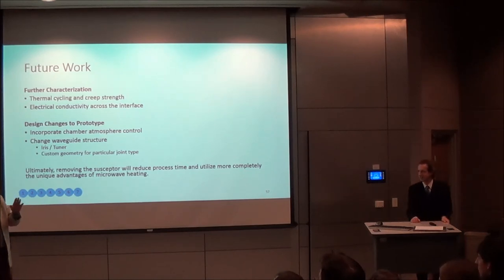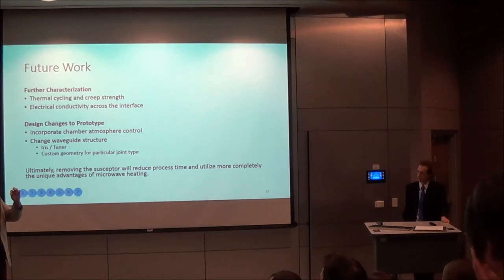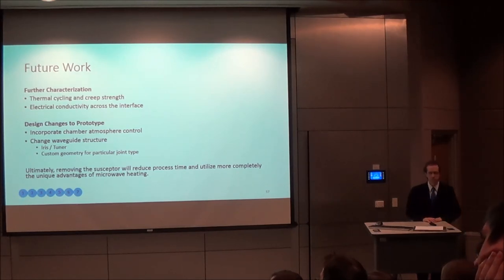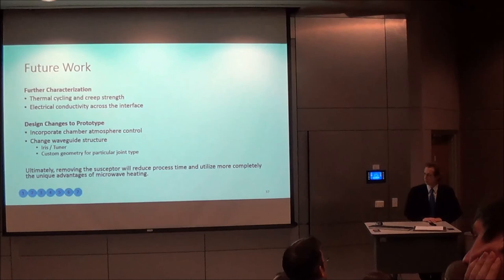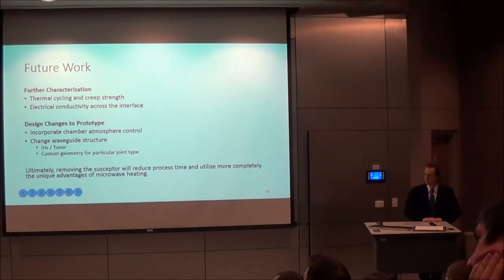Judah, you might remember, I don't know if you were there with Alan, he started with particle size and distribution, magnetic versus paramagnetic powders at the interface. And when they discovered that practically, right now, this composite, this particular dielectric for the powder is almost invisible. It basically reflects everything. We need to find a way to penetrate within that boundary, and we don't know how to do it yet. Maybe Kyle or whoever will start this. We need to penetrate because it acts like a reflector. That interlayer right now acts as a reflector, and we need to penetrate. Maybe changing frequency. We don't know how. But that's the idea, to keep melting that powder internally.